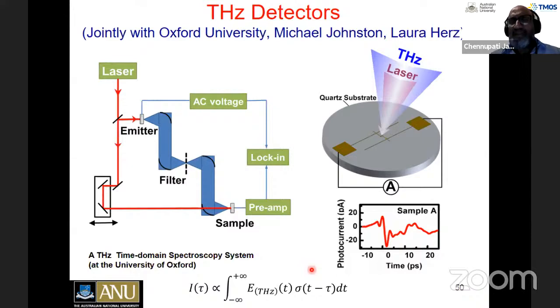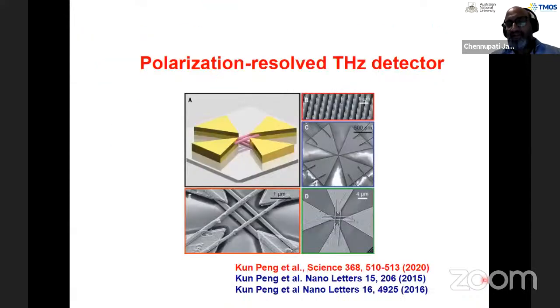And Kun Peng, during her PhD, developed a wide variety of gallium arsenide nanowire terahertz detectors and then indium phosphide terahertz detectors. But to cut the long story short, let me share with you her most recent results, which we published last year. She developed these polarization resolved terahertz detectors by using these bowtie antennas and placing the nanowires in orthogonal directions, and thereby you could measure both X and Y polarization of this terahertz pulse, for example, here.